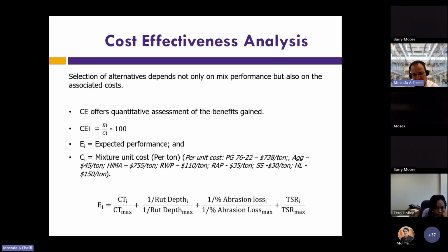To determine the cost, we obtained the cost from different sources, from contractors, from the DOT, and mostly from the Louisiana region, but also from Region 6 in general. And the expected performance, you can see at the bottom here. We combined the four performance measures that we have: the CT index of the mix divided by CT maximum, the rut depth, the Cantabro loss, and the TSR. All of these will give you the effectiveness of the mix. So this method is relatively simple, but in my opinion, it's very accurate because you have the performance and the cost of the mix in one ratio.